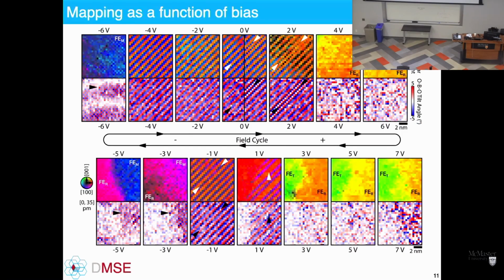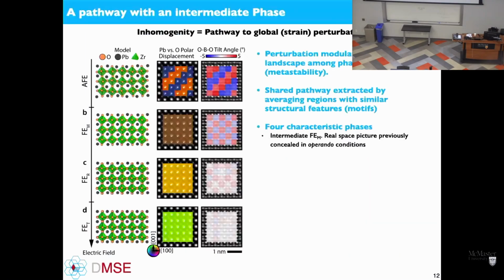You can see these defects pop into existence, these ordering, the stacking sequence ordering that then disappears into a ferroelectric rhombohedral phase that we can map out from that octahedral tilt. And this converts from rhombohedral into tetragonal at higher voltages and goes back to that antiferroelectric structure at 0 volts. And this is repeatable. So we're not just one measurement, but we can repeat the same experiment over and over and over in the microscope and get statistics on what's going on here.